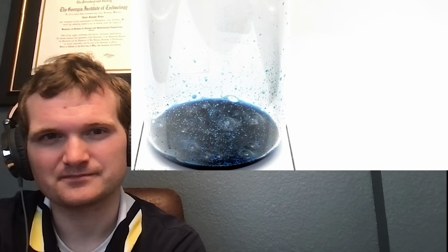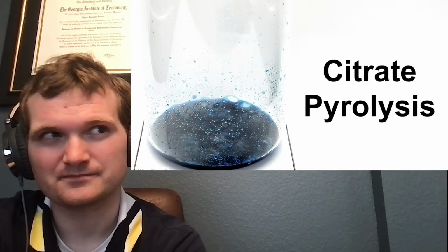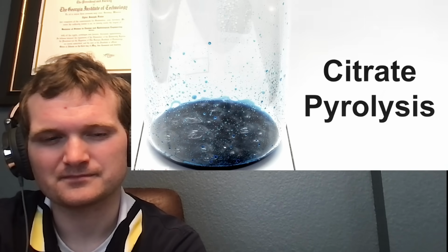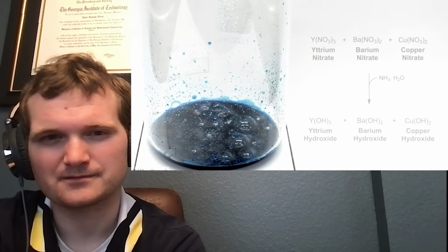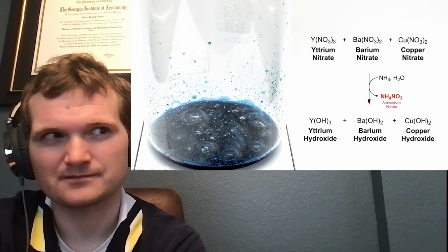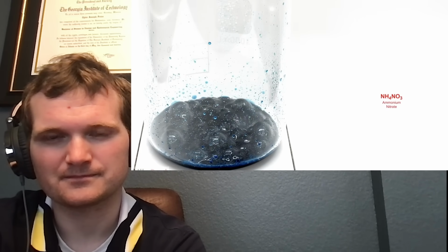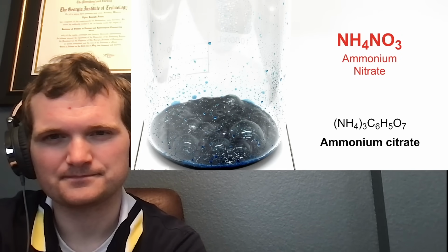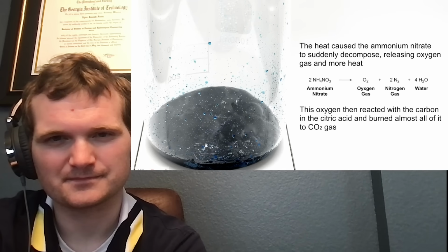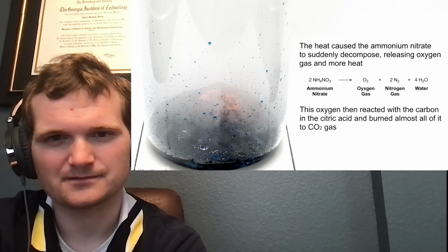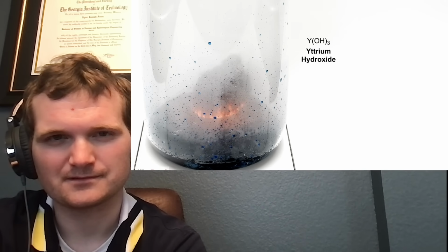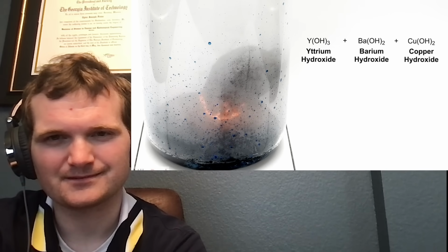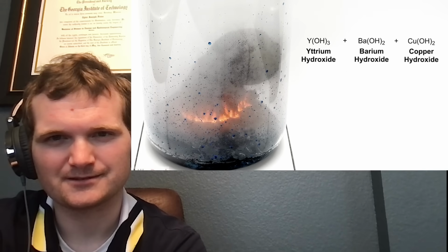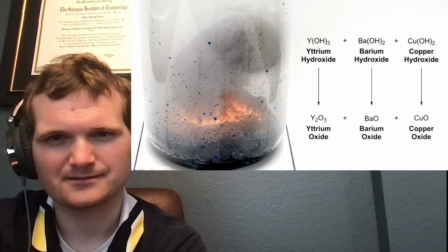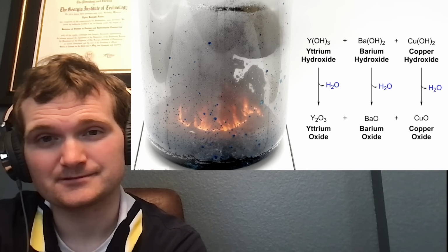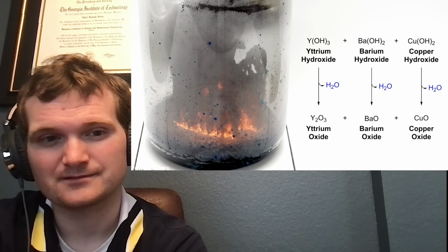Now, in terms of what was actually happening here, it was called a citrate pyrolysis reaction. Just before, when I had added all the ammonia, it had turned all the metal nitrates into hydroxides, but it had also made ammonium nitrate. This was a really strong oxidizer, and all the ammonium citrate was a good fuel. When the temperature was high enough, it triggered a reaction between the two, and it caused it to burn. All the yttrium, barium, and copper hydroxides were mixed in here as well, though, and the heat of the reaction caused them to decompose. It turned them all into their oxide forms, and it also made a lot of water vapor, which was why the side of the beaker kept fogging up.